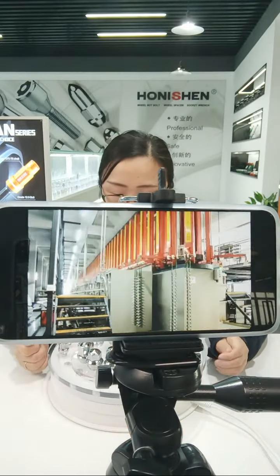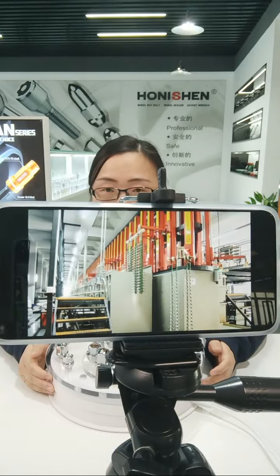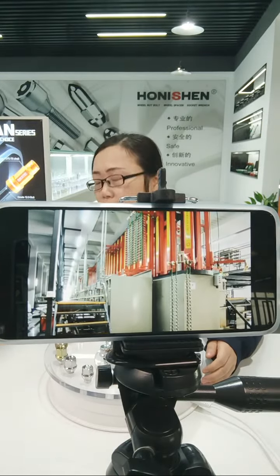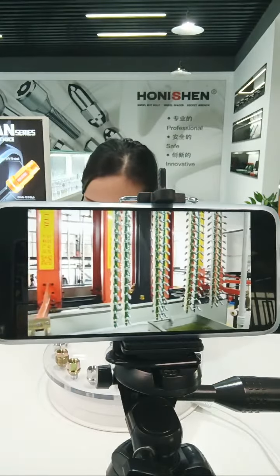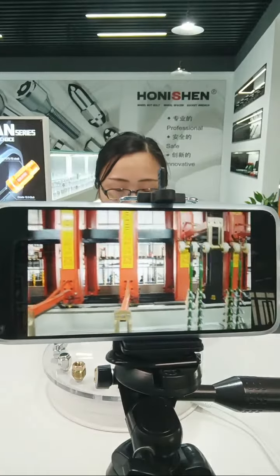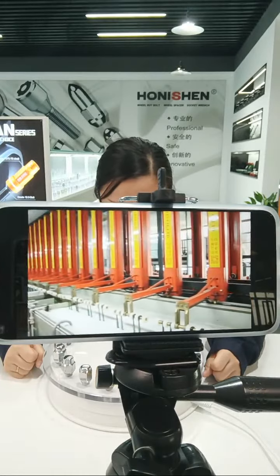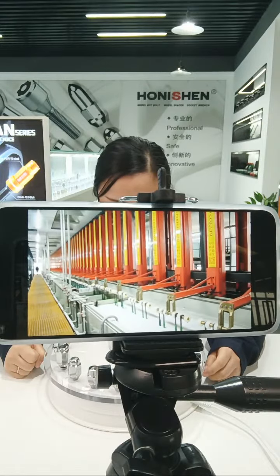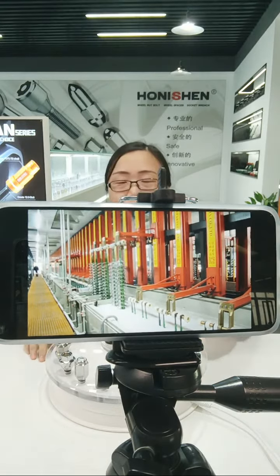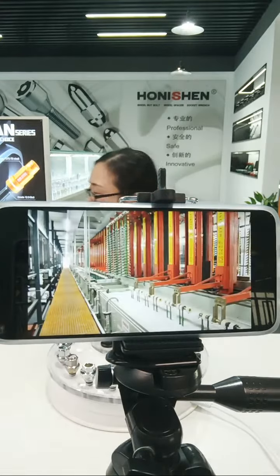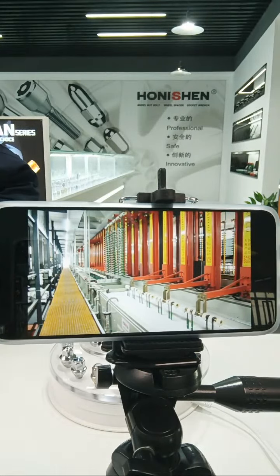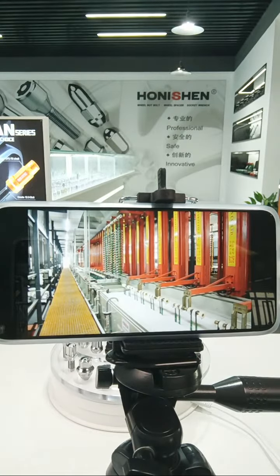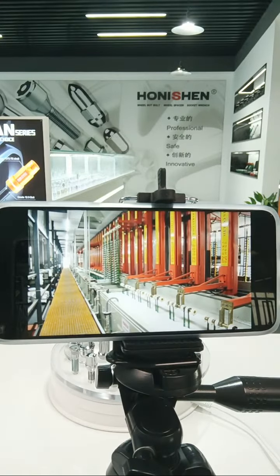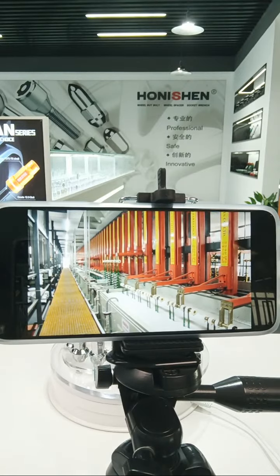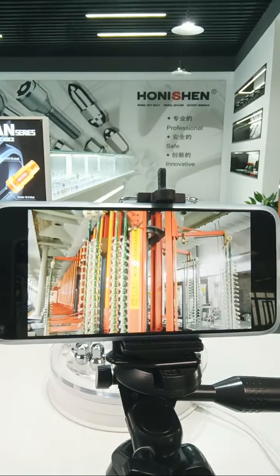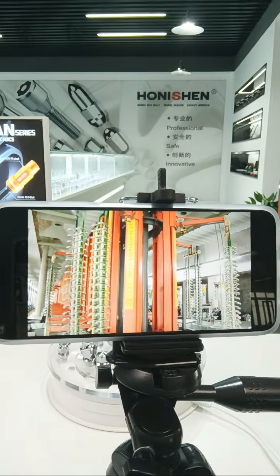Only our factory has an independent electric plating production line. We usually make 3 layers of nickel and 1 layer of chrome, and control the anti-rust performance of the product by detecting the thickness of the nickel layer and the tension difference between each layer. Our chrome plating products can pass a natural salt spray test for at least 72 hours and up to 418 hours.